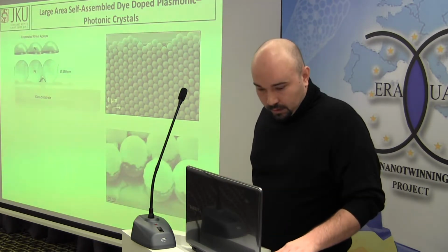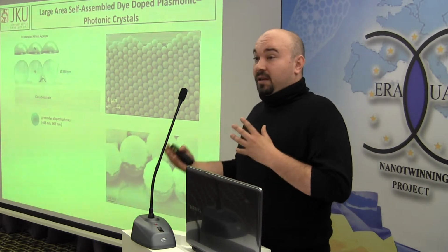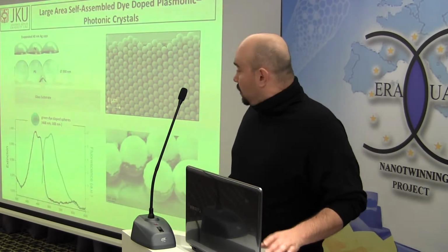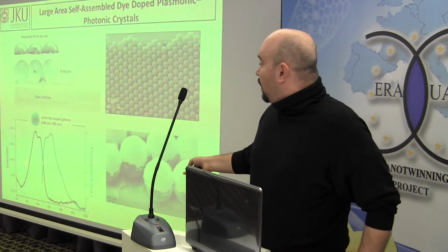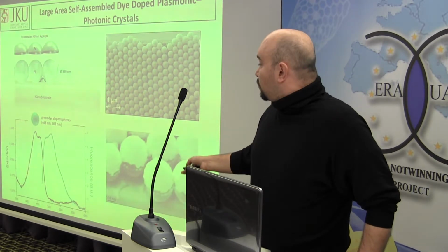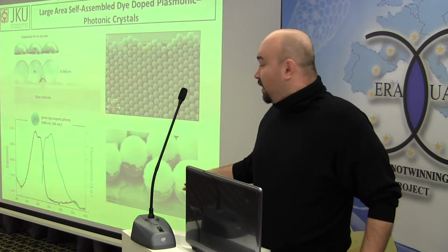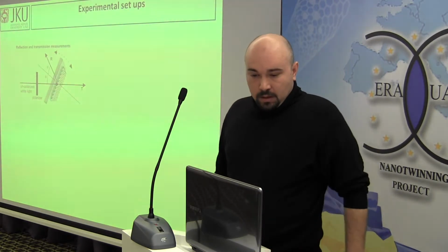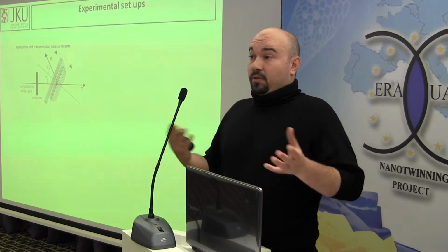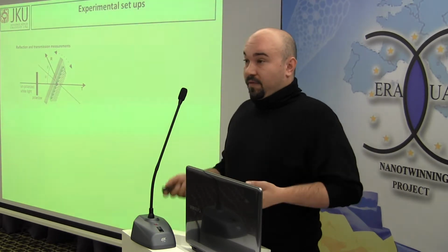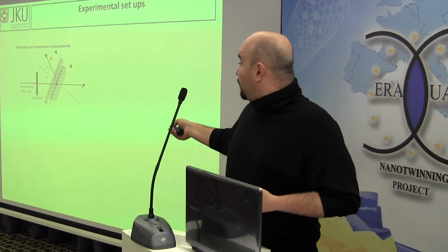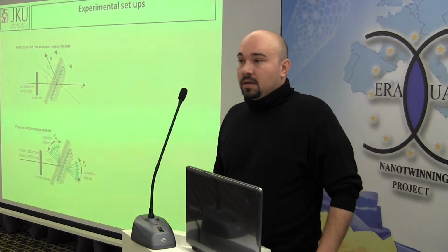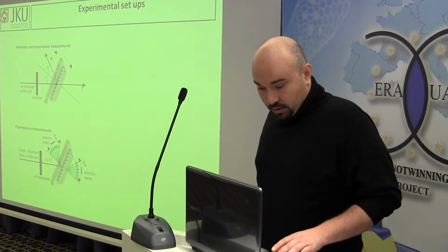image. And since we want to manipulate light, instead of using plain spheres, we use dye-doped spheres, and here are the emission and absorption spectra. So the absorption was roughly 470, and the main emission roughly 510. And our sample, in contrast to others, is transparent. So we can perform angularly resolved reflection and transmission measurements, as well as angularly resolved fluorescence measurements.